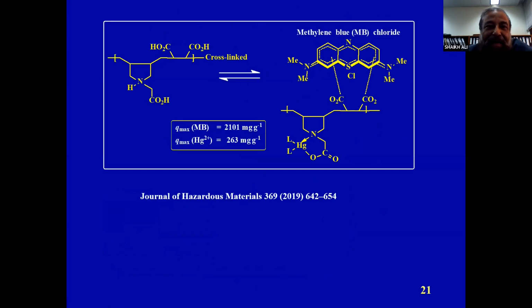Now, here we want to tell you about another amino acid, which is glycine, and a malic acid copolymer cross-linked. And this can take out the methylene blue, and this group can take out the mercury. You see the methylene blue adsorption capacity is 2101 milligram per gram, and it can remove mercury, 263 milligram per gram of the resin.